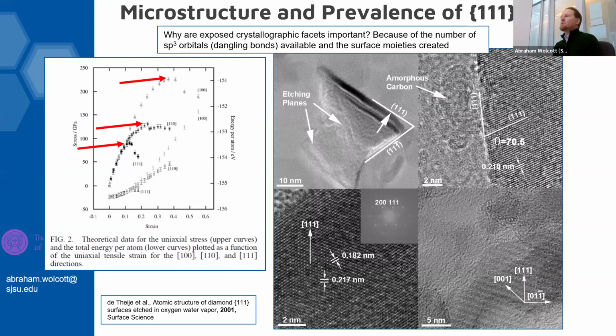Why are exposed crystallographic facets important? Answer: because the number of sp3 orbitals and their dangling bonds are available for surface moieties. The 111 crystallographic facet has a single dangling bond, while the 100 has two dangling bonds, and therefore should control the number of carbon-oxygen bonds that are formed. The difference between an alcohol, an ether, an aldehyde, a ketone, a carboxylic acid, so on and so forth.